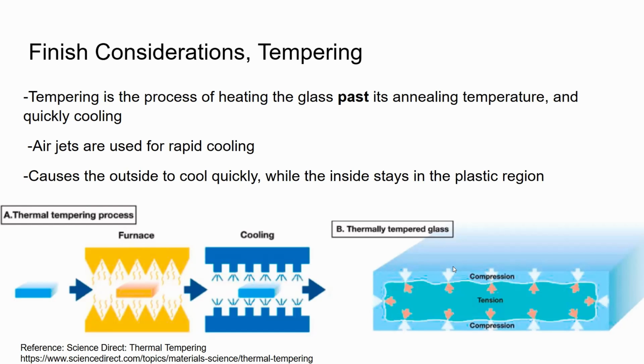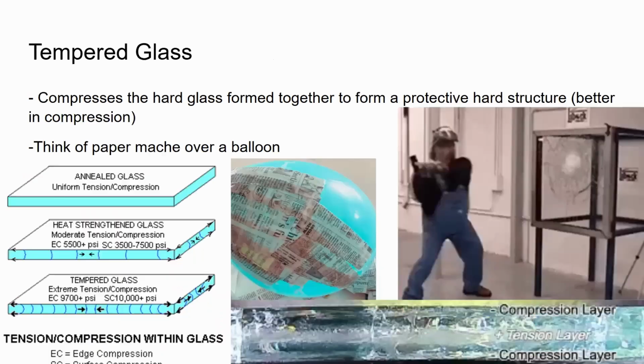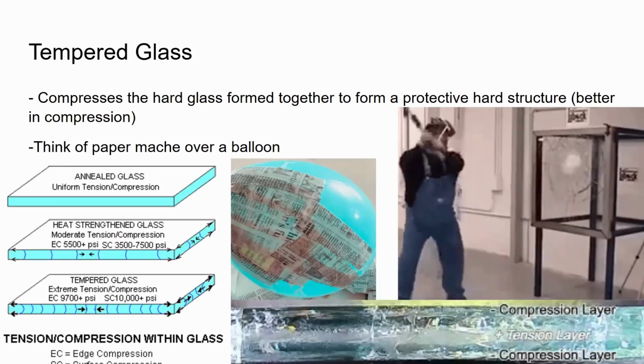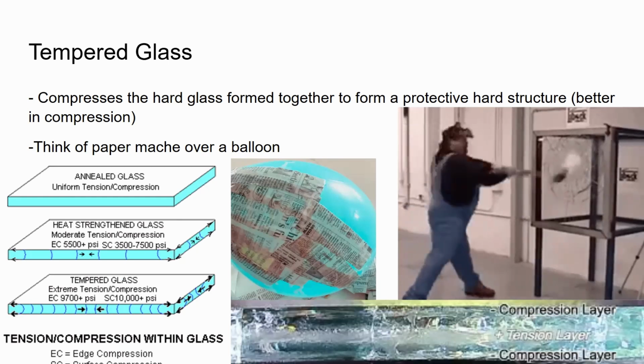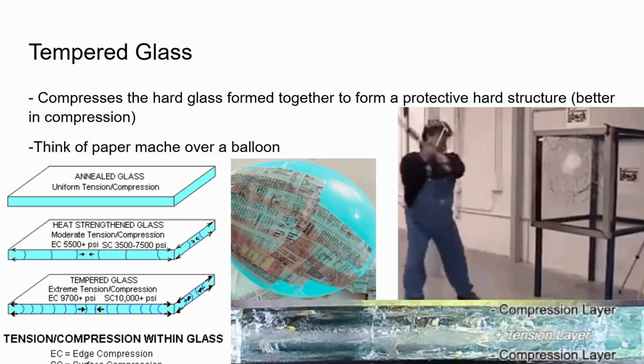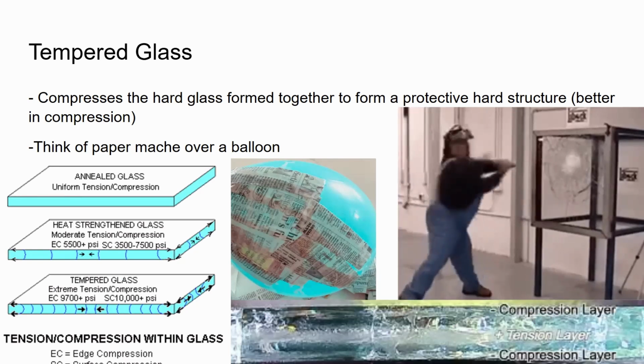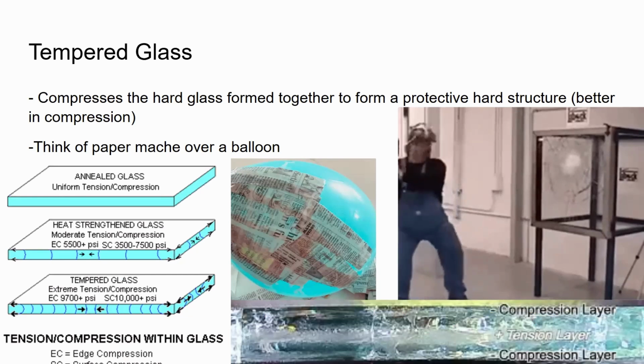Then as it shrinks, that hardened glass compresses in on itself and remains structured by its own shrinking force, similar to this image right here. The inside stays within its plastic region, so it stays a little more flexible, and the outside gets very hardened, so it can resist a lot of scratches and any kind of dents that try to hurt the glass. A great way to think about it is if you have a balloon and you put paper mache over the top of it, the outside is going to be very hard, but the inside is still flexible. So that balloon can take a lot more resistive force without destroying the inside of it.